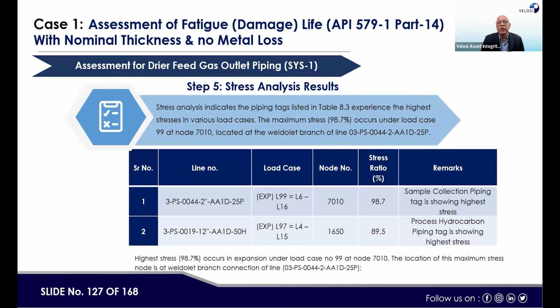Now we are showing you where the maximum stress was reported by Caesar 2. This is the case we are showing you: assessment of the piping fatigue life with nominal thickness and no metal loss. This is as new. Next would be stress at node number 7010 or 1650. Here, stress ratio is 98.7 or 89.5%, right? So the sample collection piping tag is showing highest stress. Process hydrocarbon piping tag is showing highest stress. So these are the locations where stress was reported on the higher side.